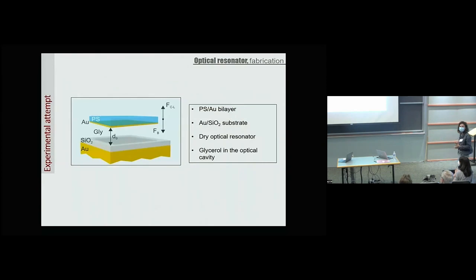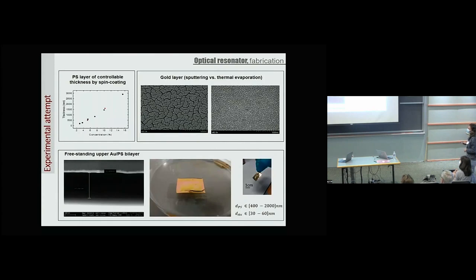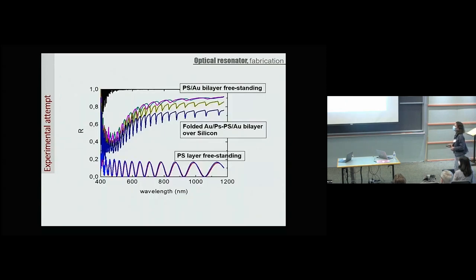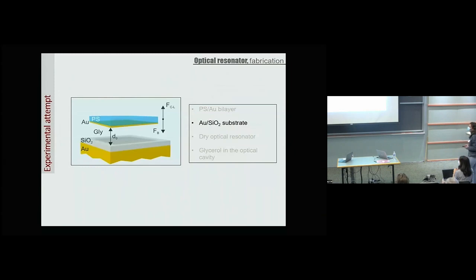So I come now to the bittersweet part. We started fabricating our system, starting with the upper part, the levitating part, the polystyrene and gold bilayer. We had a lot of control over the thickness of the polystyrene layer. We also tried different approaches for the deposition of gold, either by sputtering or by thermal evaporation. Of course, we ended up using this approach because we did a lot of tests, and the optical properties of this system were what we expected. This is how the gold polystyrene bilayer looks with the naked eye, and these are the range of parameters we could consider. We characterized them, and everything was fine with the bilayer.